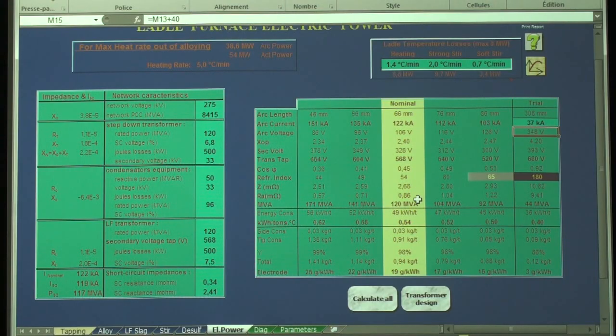But you have other possibilities, because this is manual. Then I have a huge step. I have only 44 MVA. If I give 45 kiloamps, I get 46 MVA. If I go to 55 kA, now I have a 50 MVA transformer. But you see that I have a radiation index very high.